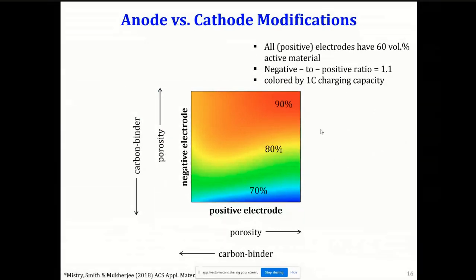So the previous one was for a single electrode. Now, in this case, we have two electrodes as a full cell configuration. And what I'm showing you on this map are different candidate electrodes, so positive electrode and different negative electrodes. All of these candidate recipes are such that you always have the same amount of active material on cathode, which is 60%. And equivalently, you have the same amount of N to P ratio, which also fixes the amount of active material on cathode. So now the only thing you are varying is the amount of carbon binder and the amount of porosity at each of the electrodes.